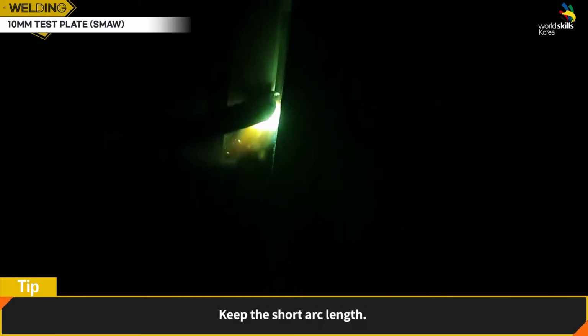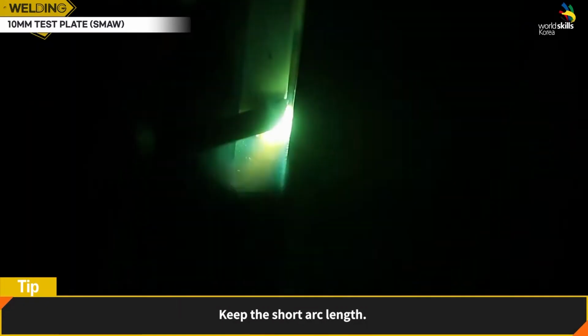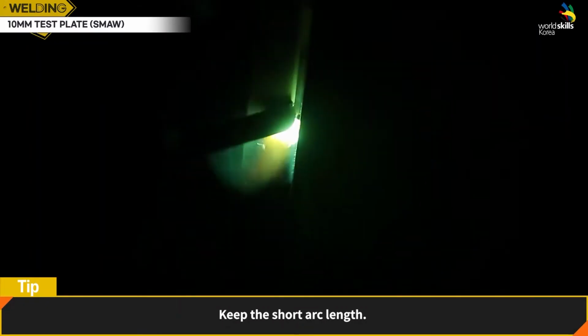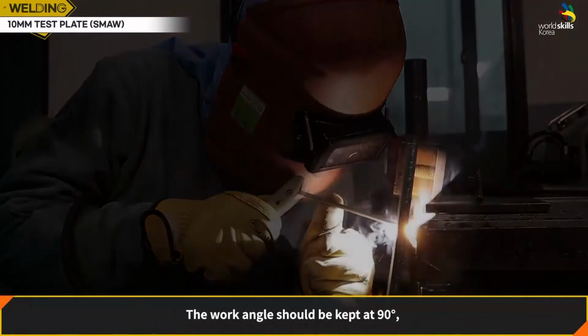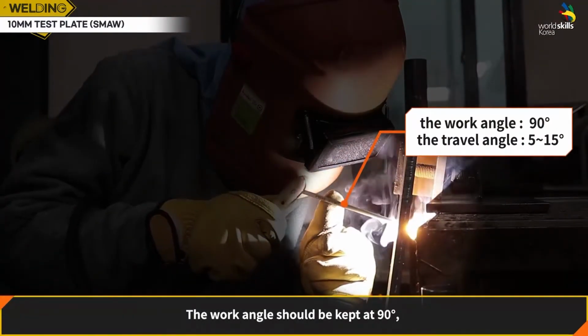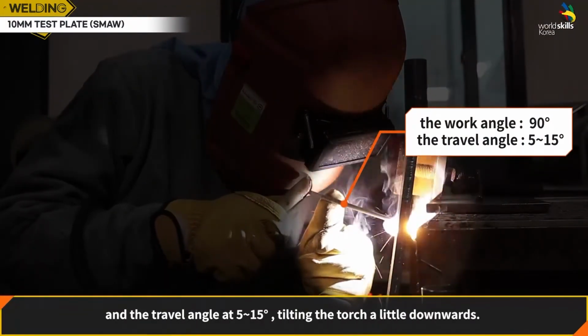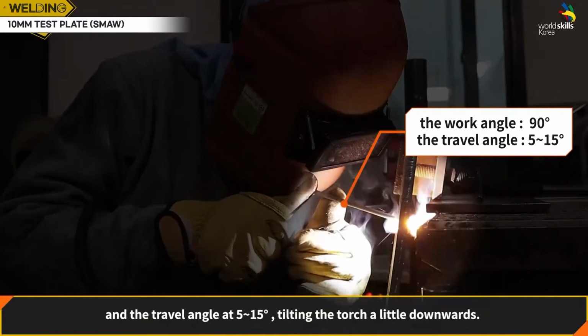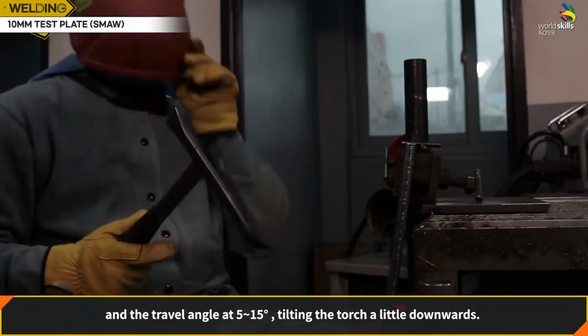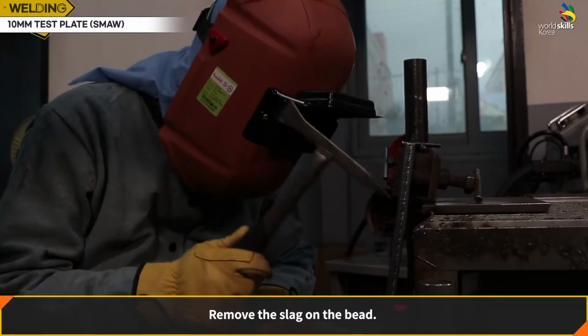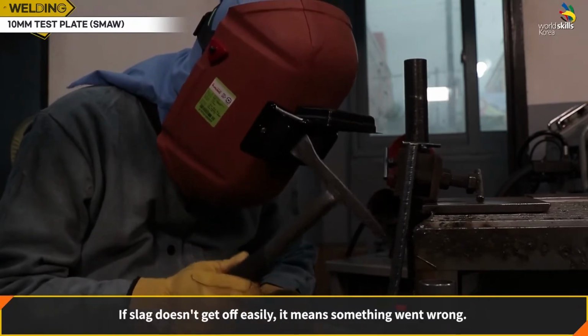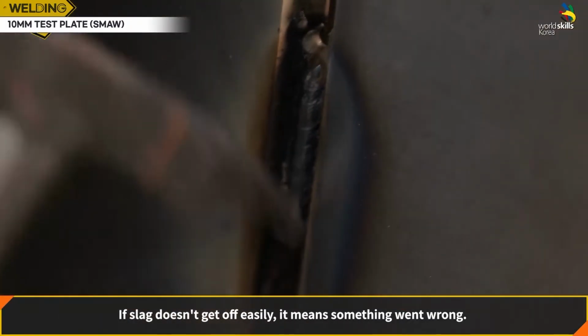Keep the short arc length. The work angle should be kept at 90 degrees and the travel angle at 5 to 15 degrees. Tilt the torch a little downwards. Remove the slag on the bead. If slag doesn't come off easily, it means something went wrong.